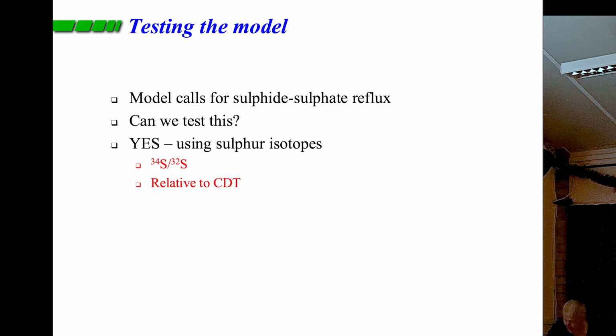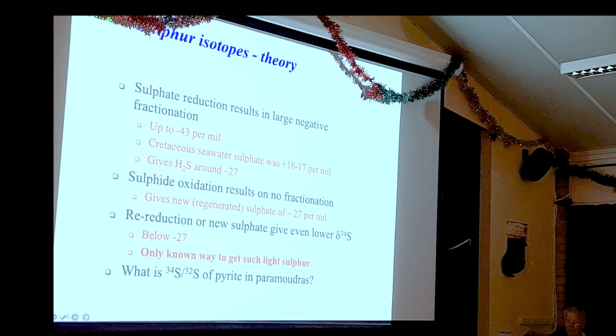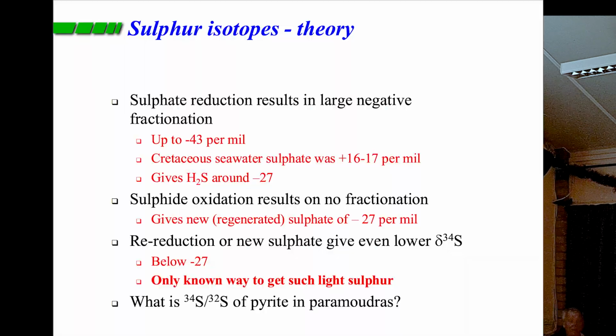What happens is when we get sulfate reduction, we get up to about 43 parts per thousand fractionation. Cretaceous seawater sulfate was about plus 16 to plus 17 per mil. And that should give us H2S, which is around minus 27, and that will then migrate back to the burrow.